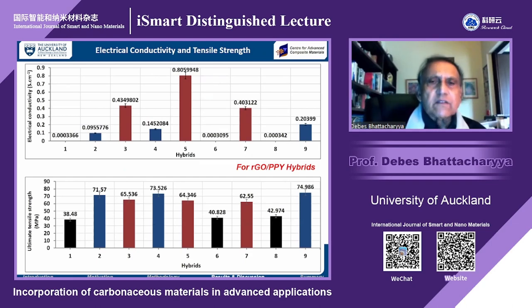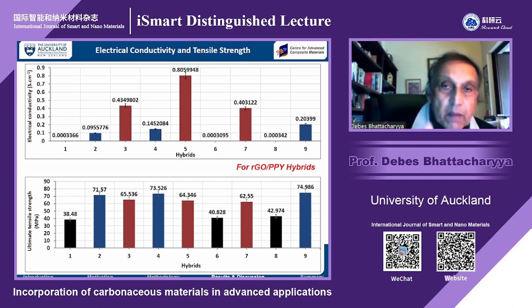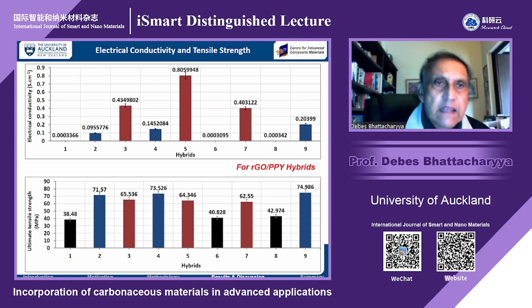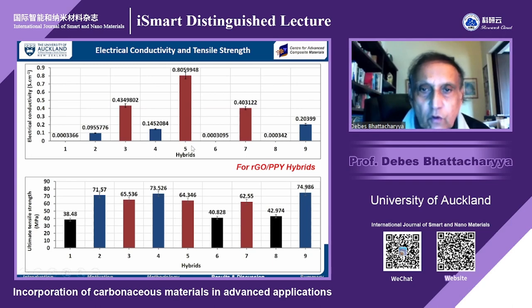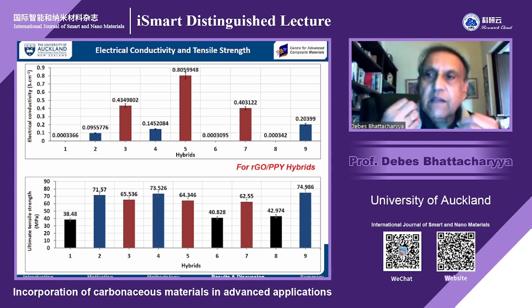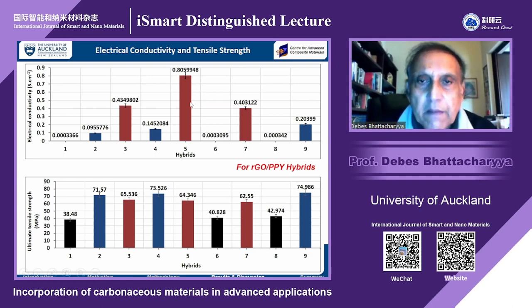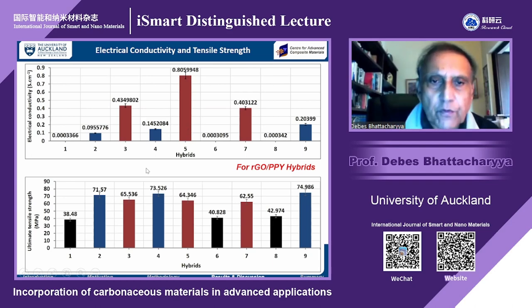So if we plot the results, well, it is conducting, but we were not happy. If you look at that, the best conductivity we could get was about 0.8 siemens per centimeter. That was for combination 5. And the second, combinations 3 and 7, had similar conductivity, but half of that value. And the mechanical properties of quite a few of them were pretty high. But if you use your engineering judgment, you will say that number 5 was a good compromise between electrical conductivity and mechanical properties. You might say, okay, I can forego conductivity a little, but increase the strength, then you can go for that.